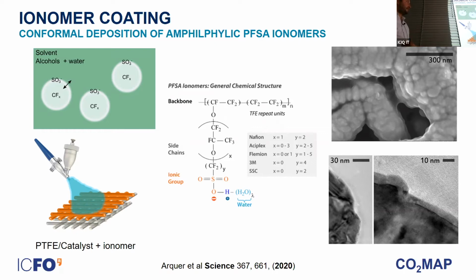So we mix Nafion, we mix alcohols and water, we shake it, we put it in a spray gun, we spray on top of the surface of the gas diffusion electrodes, and you can see here in this scanning electron microscopy and TEM how the copper fibers are covered kind of conformally with a very thin film of the polymer that we want to make, the ionomer of Nafion. You can see here a cross section at the TEM where you can see the thickness of this polymer is around 10 to 15 nanometers.